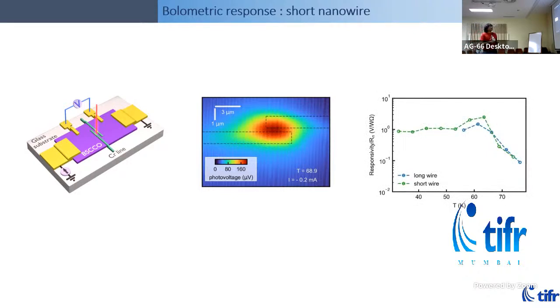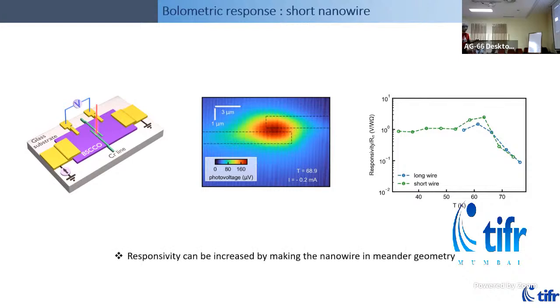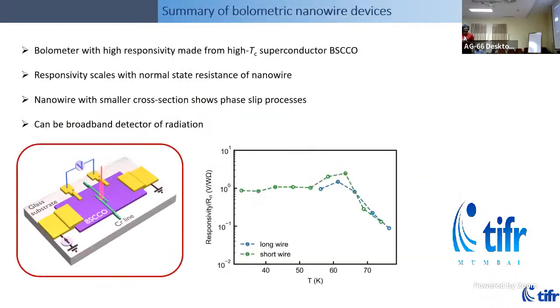If you look at the responsivity of long and short wires normalized by the normal state resistance, which corrects for the geometry, then it makes more sense to make long meandering wires, like the ones that people already use. This kind of experiment clearly shows that the architecture of making meander wires which are only 1 or 2 unit cells thick is the optimal geometry. So this is the summary of this particular part of the work, and I'm almost on time.